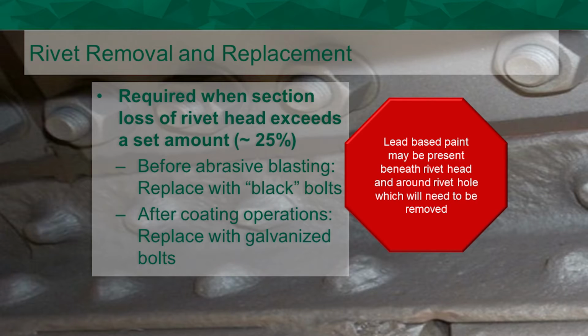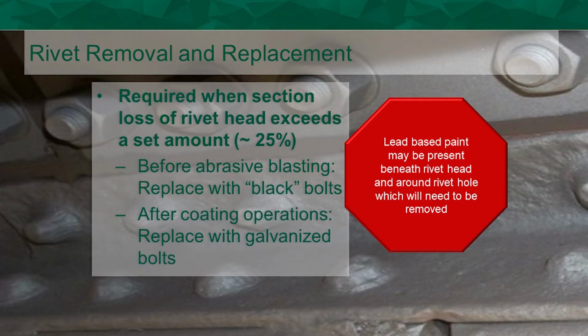Rivet removal and replacement. Typically around 25% or more, you're replacing your rivets. And if you're going to replace them before you do any coating operation, you can go with your black bolts, because then you can just abrasive blast the entire surface, including those new rivets, and then apply the coating system. If you're going to do it afterwards, you may want to think about going with galvanized bolting.